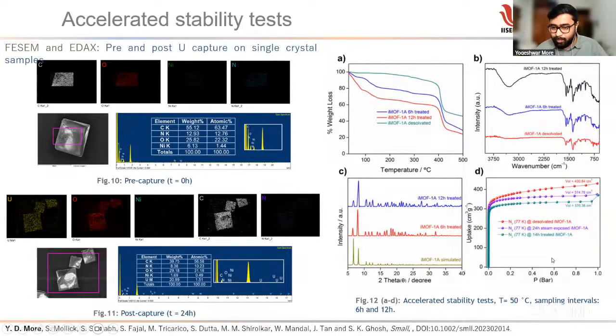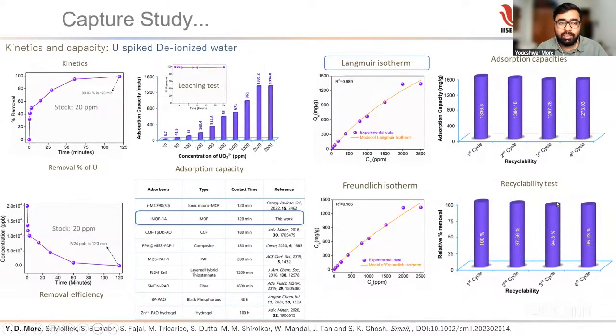We saw particularly that the desolvated MOF has a very high amount of N2 adsorption, that is 430 ml per gram. Once it has adsorbed uranium and we did a steam exposure, it goes down, and then we regenerated it. After removal of water, the pore or cavity should be empty. We saw there is no great loss in the cavity structure or the overall surface area. Once that was assured, we went for the capture study.